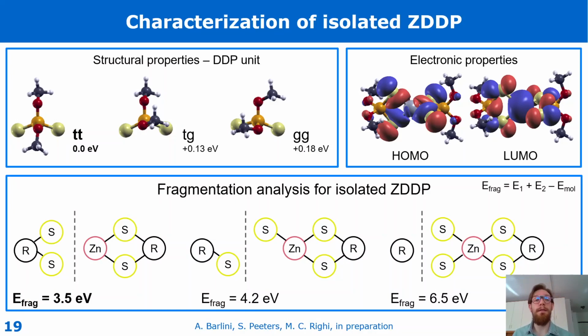So to better understand the tribochemistry of ZDDP on these lightweight alloys, we first characterized the properties of isolated ZDDP. We started from the structural properties of the DDP unit, so we found out that the trans configuration for the alkyl chains is more favorable than the gauche configuration. Then we move to the electronic properties of ZDDP, and we also consider different fragmentation patterns for ZDDP in analogy with what we have done for MoDTC. It turns out again that for isolated compounds, the most favorable way to break the molecules is by separating sulfur and zinc and leaving the sulfur atoms on the ligand unit.